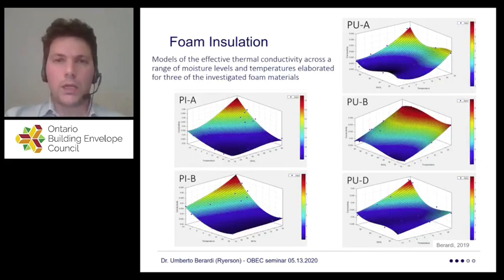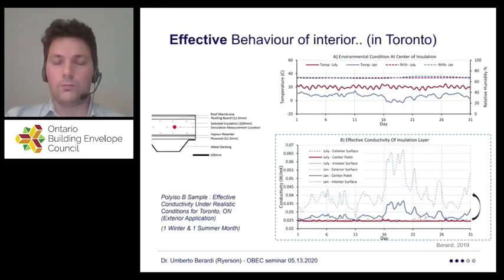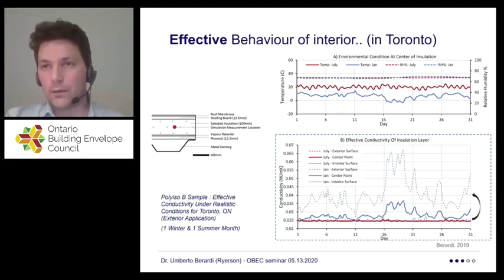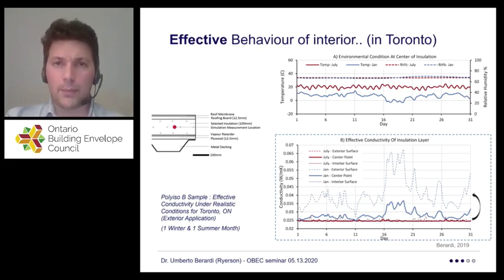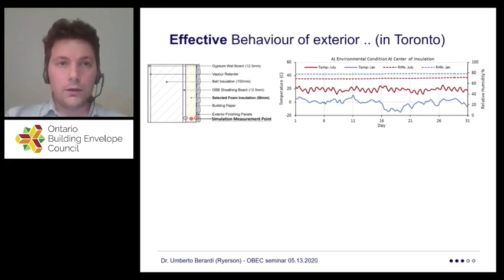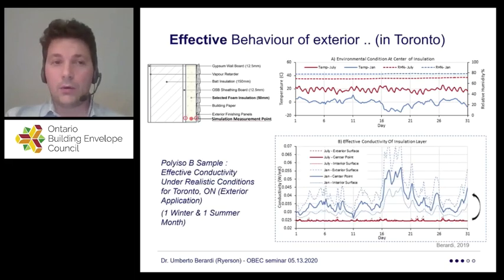So we have generated these reports with a lot of products, a lot of 3D curves, and we have also run simulations. Just to give you a sense of these simulations, what we have been doing is trying to understand, once we combine temperature and relative humidity, what happens to the thermal conductivity of those products in the real field. We have done simulations and measurements in long multi-year campaigns of different walls and roofs. Just to give you a sense of what's happening, I'm going to show you, for example, a wall. You see an insulation on the exterior side. It's a foam insulation, 5 centimeters of foam insulation. You see in the graph the temperature in terms of July and January. And here it comes what happens, for example, to the thermal conductivity.